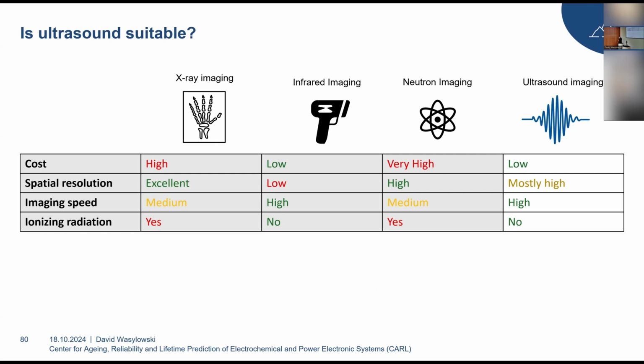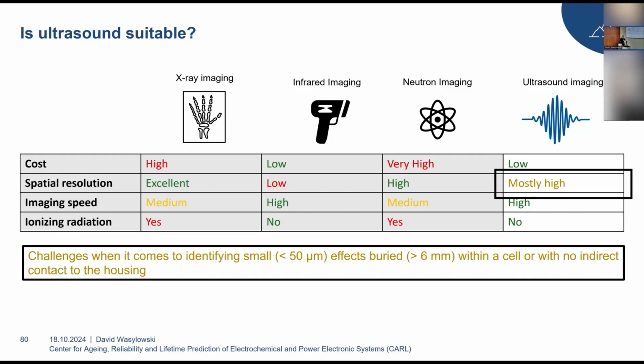But whenever we would have to image manufacturing defects or any other effect within the cell which is smaller than 75 micrometers, we would really have to tune down the spatial resolution. And typically, there is always a balance with ultrasound between spatial resolution and penetration depth. So if there was a defect buried within a very thick battery, the dampening of the ultrasound wave would be so high that the sound wave would not have enough energy to have a sufficient signal-to-noise ratio when it is reflected back at the receiving transducer. So this is most likely something that can be solved in the future with different sensors, but to this date, this is still a barrier that we need to overcome.